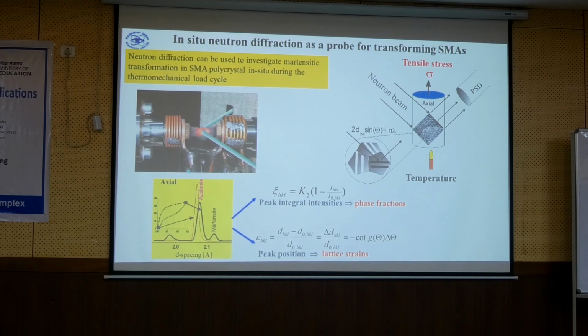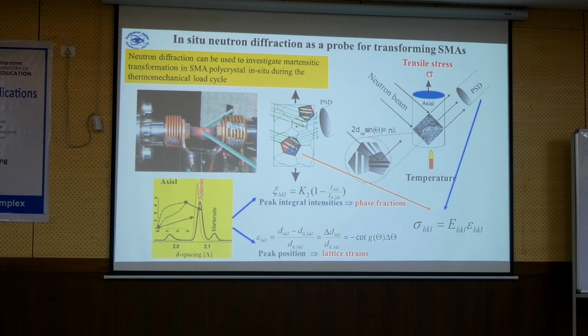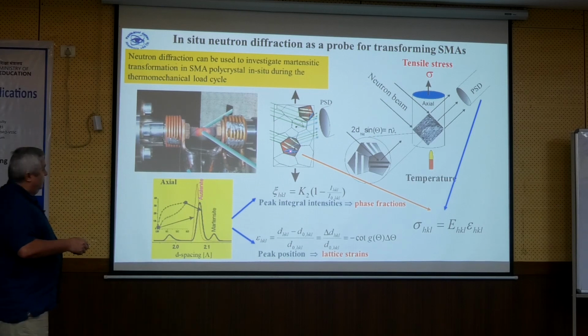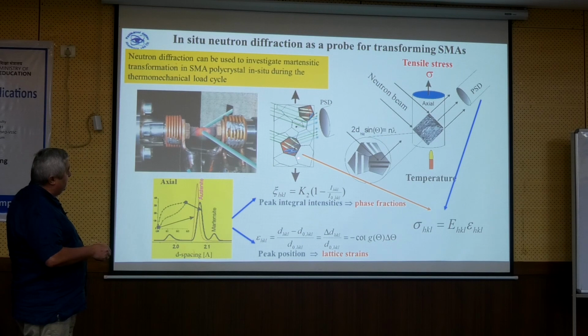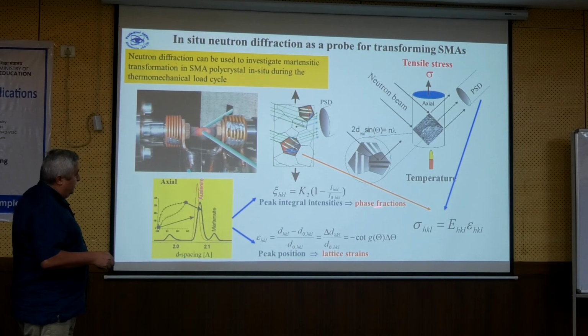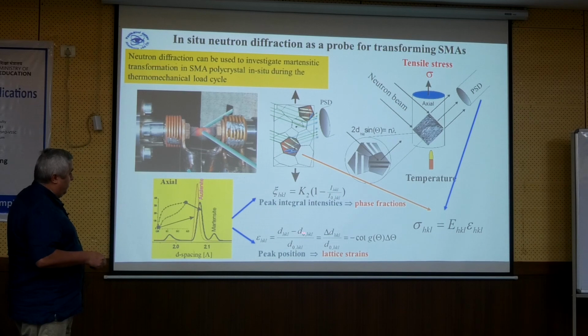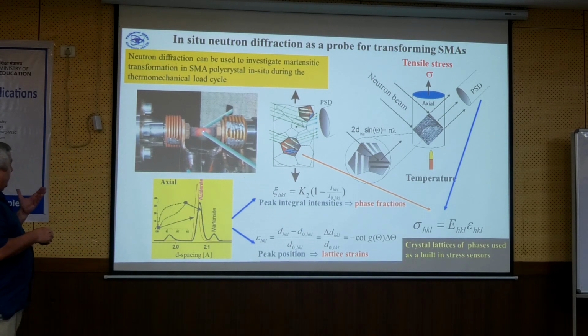In practice, it looks something like this. So you have the sample which you may heat. So if you heat and cool, you will obtain the transformation without stress, but you may also load it. And the information which is obtained is, if you have shape memory material, the red would be austenite, the blue will be martensite. So you get the diffraction pattern here by detecting the diffractive signal both from the austenite and from the martensite. As I said, we can calculate the phase fraction from the integrated intensities. From the peak shifts, we can calculate the internal stresses, and basically the lattice in the materials are like kind of sensors for phase fraction and stress.